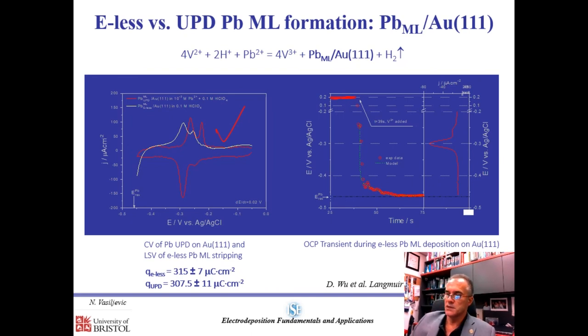The process occurs when we introduce vanadium 2+ as a reducing agent in the solution containing lead 2+, where the electrode surface is gold, for example, but it could be platinum, ruthenium, copper, etc. What we have is the formation of the lead monolayer on gold, but there's also a parasitic hydrogen evolution reaction going on in parallel.